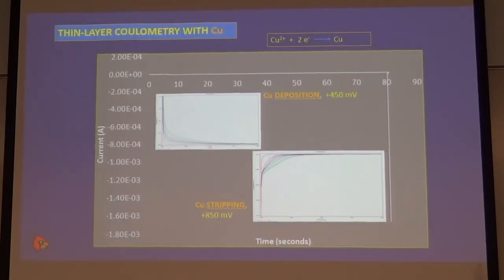These different lines are different copper concentrations. The lower copper concentrations are down here, so the signal that we're getting increases with concentration. That's good. Funny thing about copper, though, is that it's not like ferrocyanide. When we do ferrocyanide, both species, ferrocyanide and ferricyanide, are soluble. But with metals, it's a little different. Copper is in solution as copper ions, but when you reduce it, it forms copper metal. Copper metal plates out on the electrode surface. So it's a reversible process, but we call the two stages deposition, when the copper goes from ions and plates out on the electrode surface. That's the reduction step. When we carry out the oxidation, we're converting the copper to copper ions, so we're stripping the copper off the electrode surface.